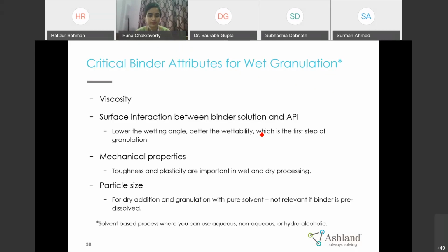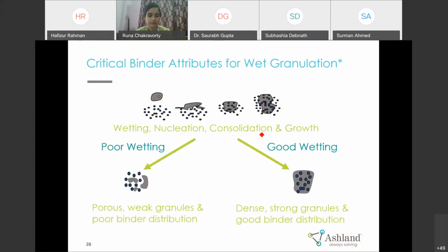And again, if you are using a dry binder and doing granulation with water, in that case particle size is very important. So what happens, if your viscosity is very high, or if your surface tension is not right, it is not able to hydrate your blend, so then it will give poor wettability. But if all the considerations which you have taken for binder selection are proper, then it will be able to wet the blend as desired.